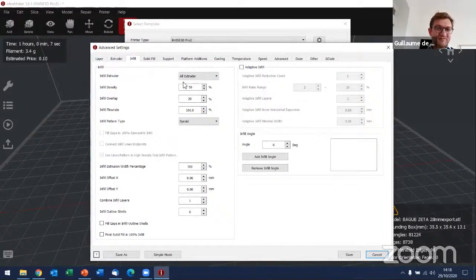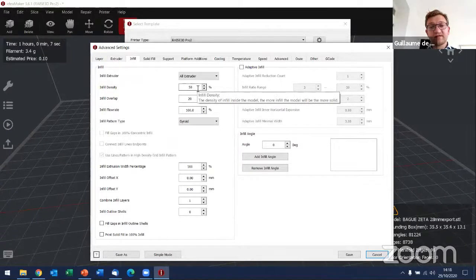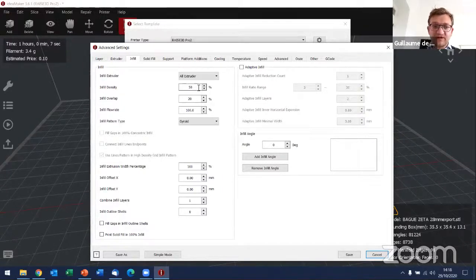We go to the third tab, infill, where we're just going to decide the density of the inside of the part. One of the big interests of FDM printing is that you don't need to print a fully dense part. You can make the inside completely hollow, or you can fill it with any kind of structure and with any kind of density. So here we decide to put 50%, which seems again a good figure, of infill, and we can choose to have honeycombs, grids, gyroid, whatever. We'll start with honeycomb, which is a very simple, very well-known parameter.